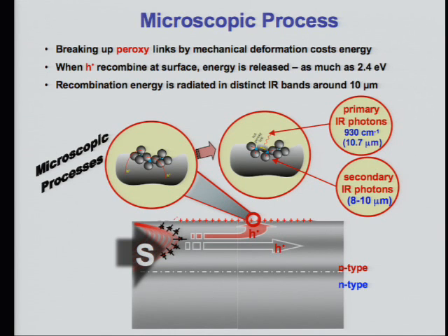High purity fused silica. This is the main enemy of long distance optical cables that would transmit optical signals in the near infrared, because that is a defect that is easily activated and then creates color centers which mess up the transmissivity of long-term 100-kilometer long optical fibers. So this has attracted a lot of attention also from theoretical people, and they calculated the energy of these vibrations. And from this we know that at least at the ground level, the last step, as this would tumble down the vibrational excitation scale, is at 10.7 micron or 930 wave numbers.